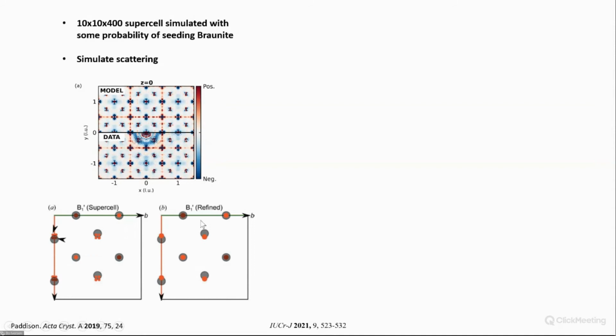And then you can ask, what about these residual density features? Because one thing I say is that the average density should also show disorder. And in fact, if you condense all these many supercells down, you get exactly the extra density around the metal sites where we refined it. So I think this model is correct.